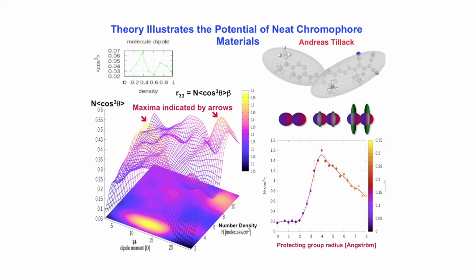The other thing that he showed by considering modification of the chromophore to change its shape was that yes, you could continue to increase acentric order as you increase the radius of your protecting group, but note you go through a maximum in the plot of electro-optic activity, or the product of number density and order parameter. Because as you're increasing this, you're also dropping the chromophore number density. So these two terms, number density and acentric order, start to compete, and you end up with a maximum. So it tells you you don't simply want to blindly modify chromophores.